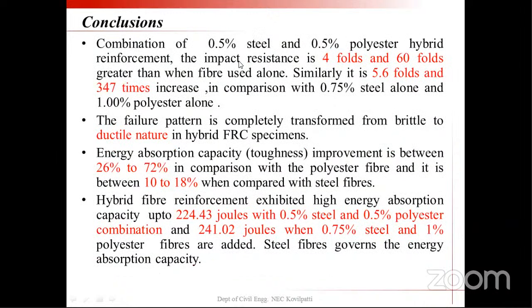And whenever you're thinking about the impact resistance, it is improved from 4 folds to 60 folds. And in ultimate crack also, it improved from 5.6 folds to 347 times. All these improvements are only because of the incorporation of hybrid fibers. So the failure pattern is proven through the photographs. All the failure patterns have been observed as ductile failure, and energy absorption capacity, toughness, has been improved from 26 to 72 in comparison with the polyester fiber, and it is between 10 to 18% when compared with the steel fiber. So when we compare with pure steel fiber, the energy absorption capacity improved up to 18. When we compared with the pure polyester, it has been improved up to 72%.